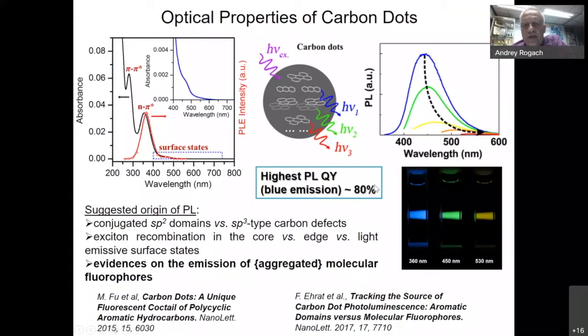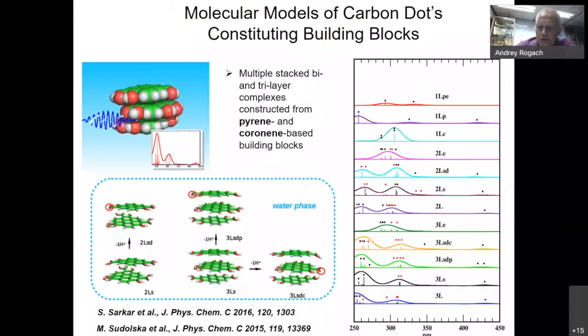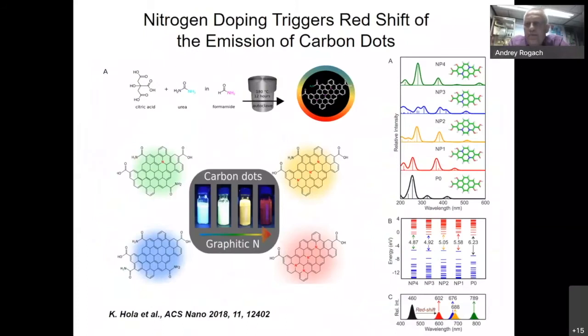80% is easily possible. This so-called photoluminescence quantum yield, I hope some of you know what this quantity tells us. It means that from 100 photons used for excitation of this material, 80 photons will be re-emitted. So this is a very important characteristic of any light-emitting material. Initial papers on carbon dots, most of them, reported blue-emitting particles. But definitely people want to make them emit any other colors. And in this story here, which was also supported by theoretical modeling, we tell people that one way to shift their spectra to longer wavelengths is to bring more and more nitrogen inside carbon dots.